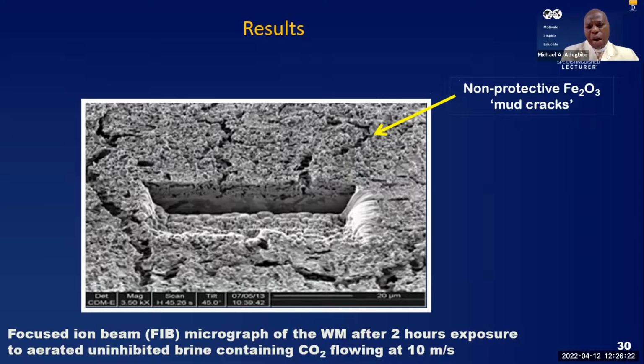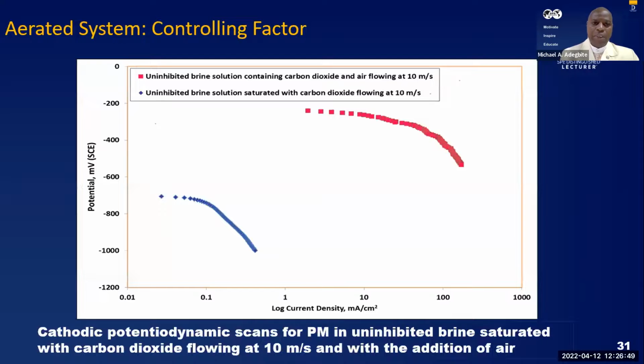We're looking at the morphology. We see mud cracks, meaning the surface protection, or the corrosion product, does not offer protection to the underneath layer. And that's what we have here. Because it does not offer protection to the underneath layer, it means corrosion goes on anytime there is flow, regardless of the corrosion product on the surface. The underneath layer is not protected.